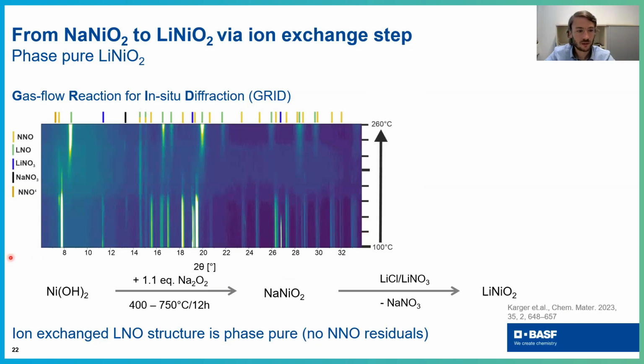And this is actually very interesting. If you look at what is happening here, at these first reflections, which were assigned to our starting material, sodium nickel oxide, you see that there's a new reflection, which is forming already at quite low temperature. I think this is something around 120 degrees. And this is actually a kind of dissociated sodium nickel oxide, which forms at low temperature where nothing melts.